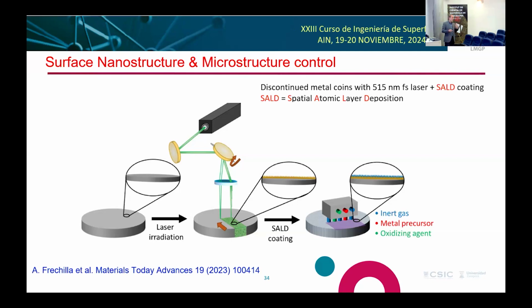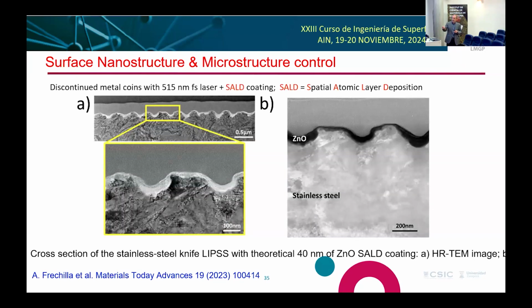And in this case, we combined what we did with David Muñoz, which is not the way we did it in the European project, where we deposited a layer of an oxide over a substrate and then recrystallized this layer with the laser. In this case, what we did is we performed the nanostructuring of the substrate and then filled in with the SALD coating, just to see if we were able to maintain that. And we do that, and you can see we can get this very nice LIPSS nanostructure, with the coating made by SALD.